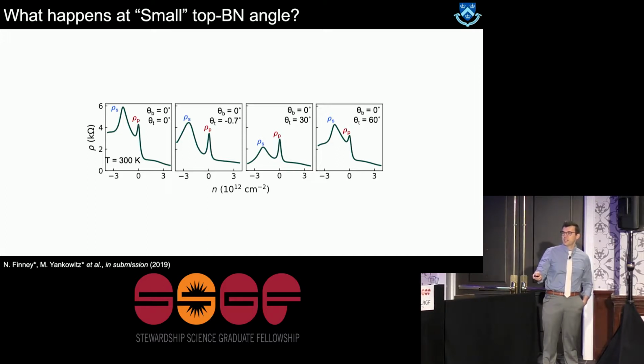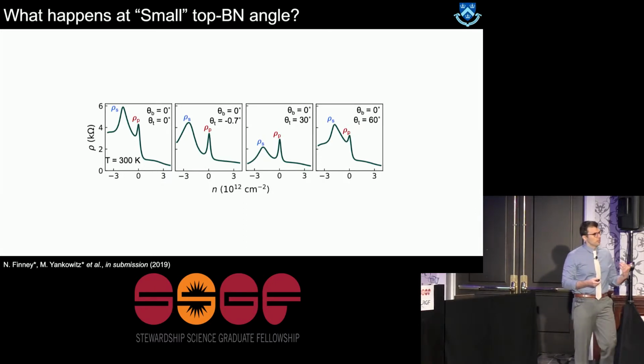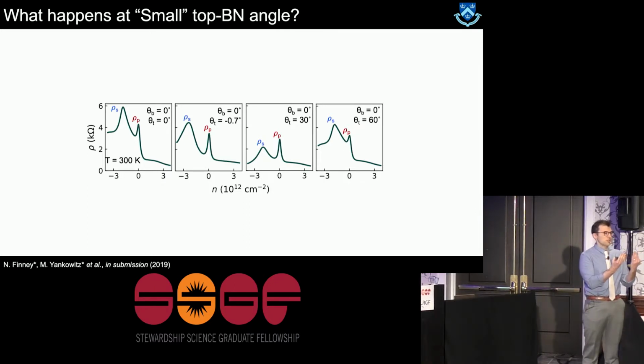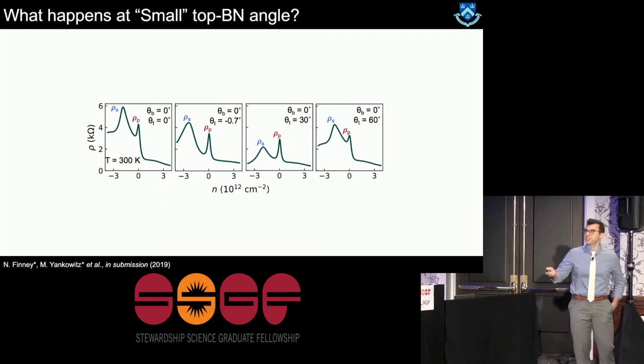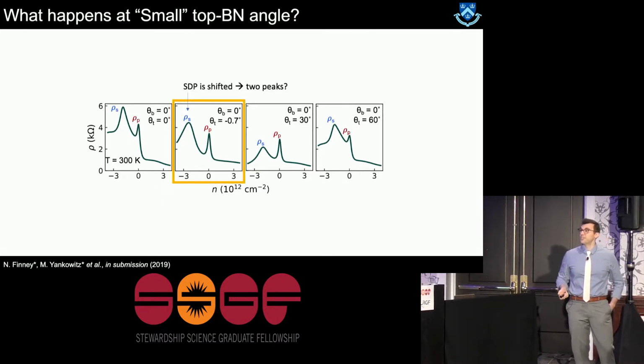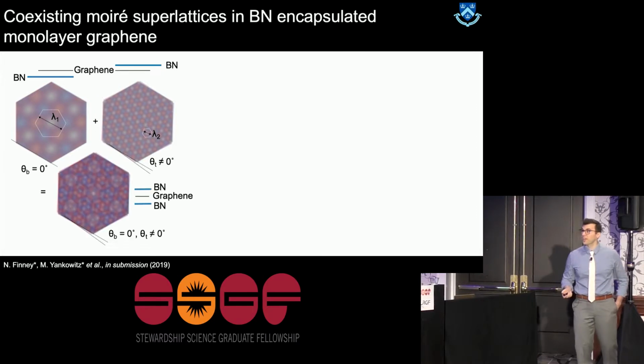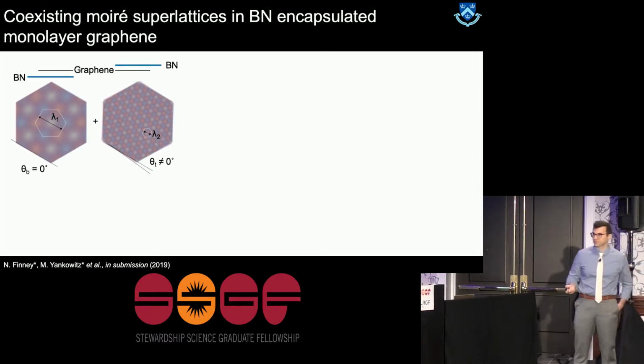It is still enhanced. But more importantly, it has shifted, which basically means that there could be two peaks working in concert to generate this peak. Resistance peaks don't add in superposition, but they might smear together at room temperature, so you can't quite see the two original peaks. So again, we take this system down to base temperature. Okay, this is what the sweep looks like.